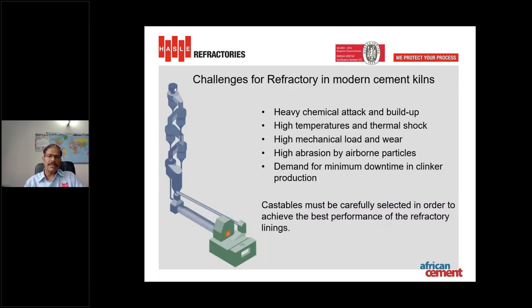So in modern days, the major challenges for refractories in modern cement kilns are heavy chemical attack and buildup, high temperature and thermal shock, high mechanical load and wear, high abrasion by airborne particles, and also the demand for minimum downtime in clinker production. So all the plants need to be very careful when selecting refractories and castables to get the best performance out of the refractory lining.